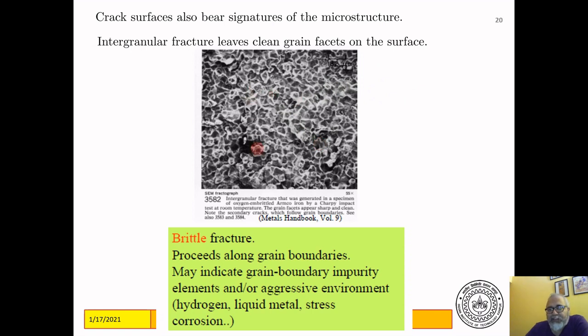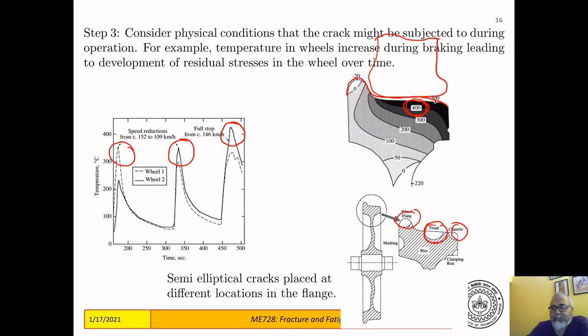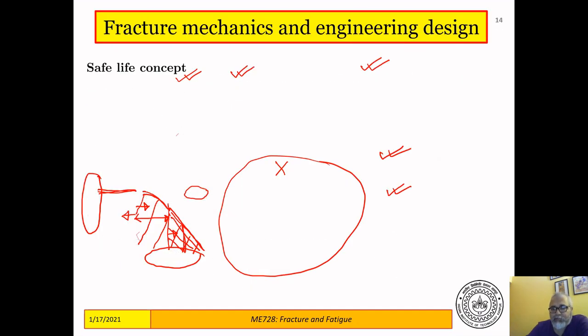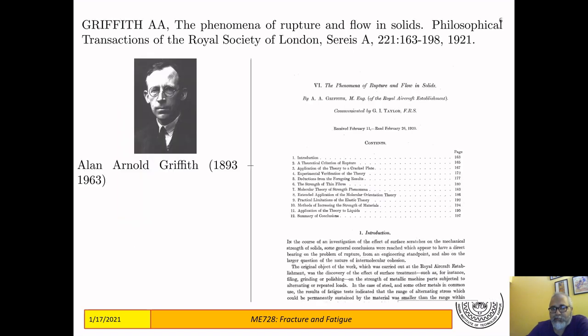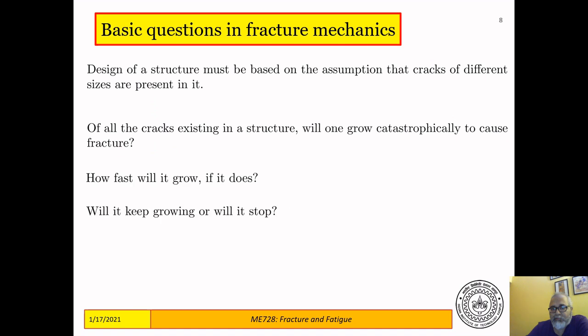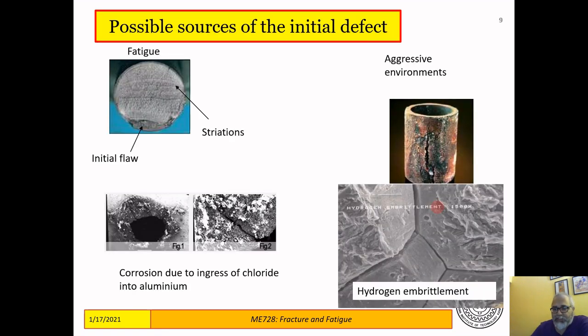This clearly tells you that these are intergranular failures. So if you have grains in the material that are shaped like this, these are rough grain shapes. And then intergranular fracture means, like we saw for the hydrogen embrittlement case, so this is a typical case of intergranular fracture, where the cracks always propagate along the boundaries of the grains.